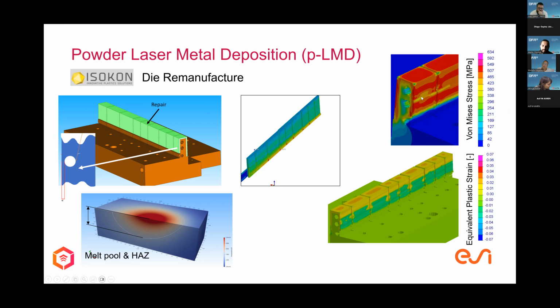And the second aspect we're looking into is usually the deposited layer has the highest stresses. So if the layer is very thin, like a very thin foil, you can indeed deposit on it, but it will not withstand these stresses. So we are looking at the stresses and the corresponding plastic deformation to make sure that when we deposit the material on these surfaces, it will also be of good quality and withstand these stresses.